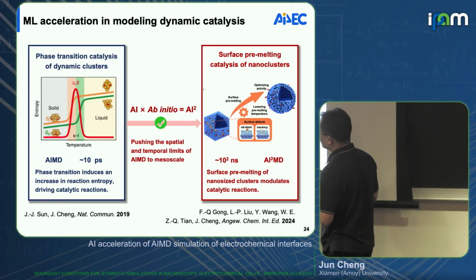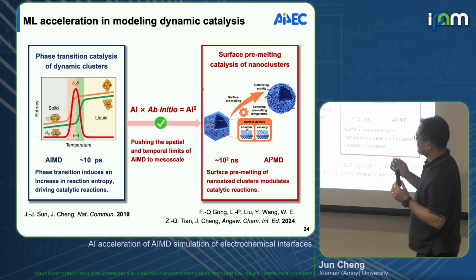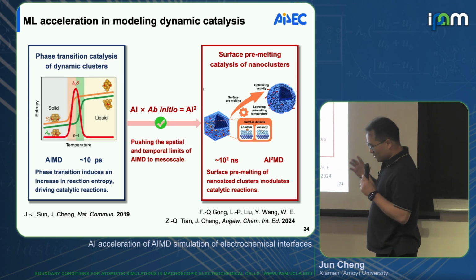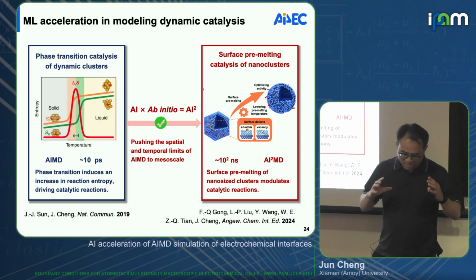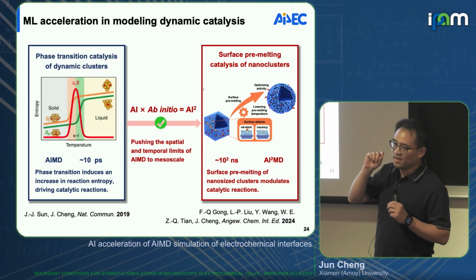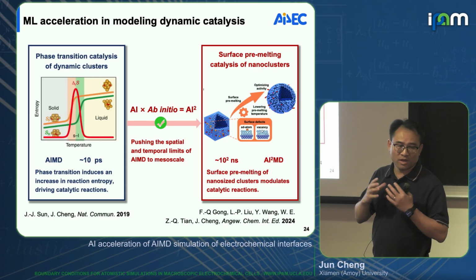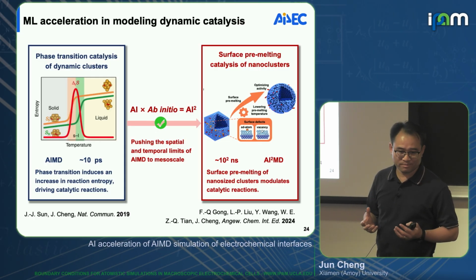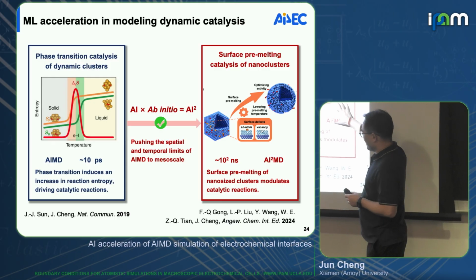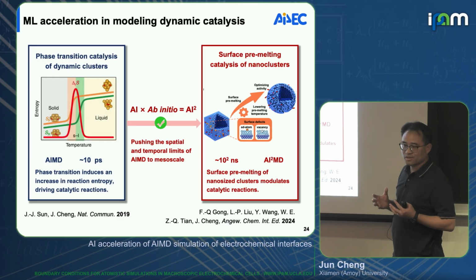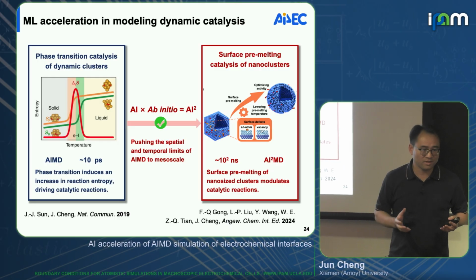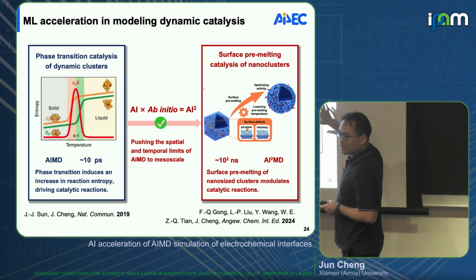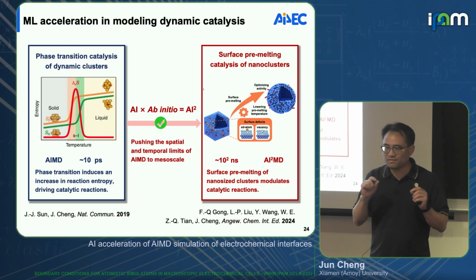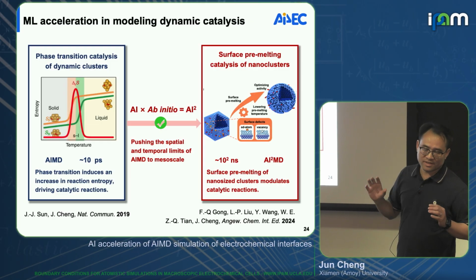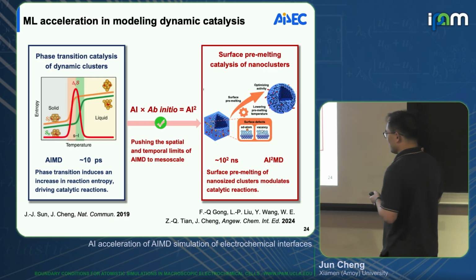So using the ab initio molecular dynamics, we show this phase transition catalysis for this very, very small system. But you wouldn't think of it, because in catalysis we normally have nanoclusters, right? You wouldn't think a small change of the state of the surface adsorbate would change the whole phase behavior of the nanoparticle, right? But what we show in the following is that we can now train a machine learning potential to simulate a much larger nanocluster. And it turns out we don't need the whole cluster to melt, right? Only the surface one or two layers of the metal melting will lead to this phase transition